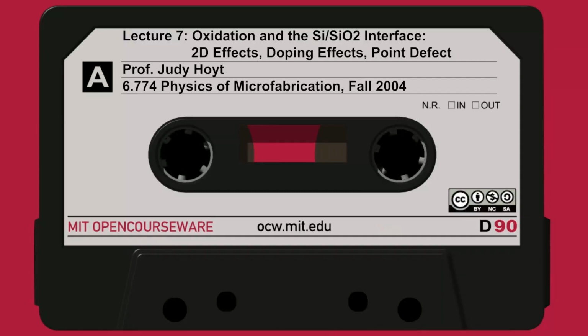And in fact, if we go to slide 32, people had an idea what it might be. Maybe it's a chemical effect of the dopant, perhaps. But people liked this model better. People liked the idea that the vacancies available in the near-surface region are important to the oxidation process. So anything that caused vacancy concentration to go up might cause the oxidation rate to also go up.